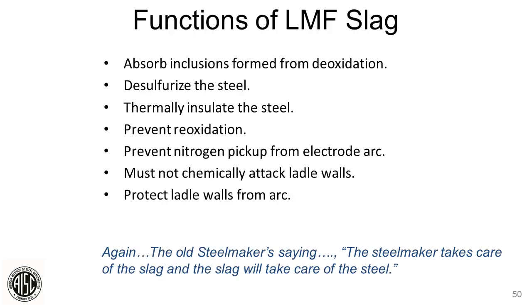So the functions of the LMF slag are to absorb inclusions, desulfurize the steel, thermally insulate the steel, prevent reoxidation, prevent nitrogen pickup, protect the ladle's refractory from being attacked, and also protect it from the arc of the ladle furnace. Again, make the slag, make the steel. Next slide, please.